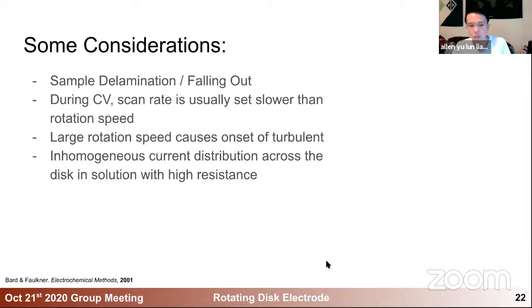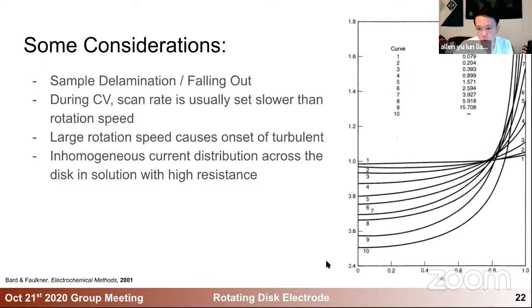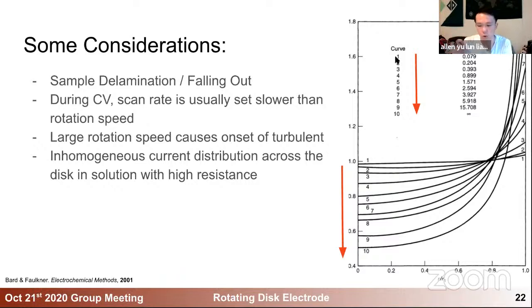And the last thing is a little bit more tricky. Most of the time, this is not a problem if your electrolyte has a low resistivity, like water with high salt concentration. But if your electrolyte conductivity is really low, then the current distribution across your disk is not even and will actually be really uneven. For example, if you see the graph on the right, you go down from curve number one, where they assume the electrolyte conductivity is really high.